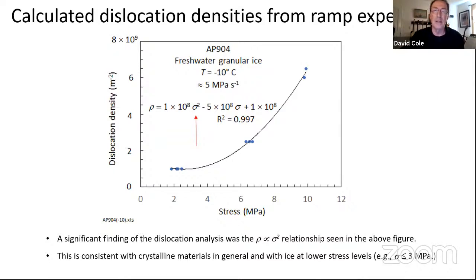By looking at the areas and doing an analysis we've talked about for these samples at various increasing peak stress levels, this is what I found. The dislocation density associated with those increasing hysteresis loop areas follows a stress squared relationship, which again was another startling factor, because this is exactly the kind of behavior one gets at low stresses. I think the internal dislocation dynamics are quite different, but the fact that they're being produced according to this same stress dependence is, I think, remarkable, and it makes life a lot easier in terms of the modeling here.